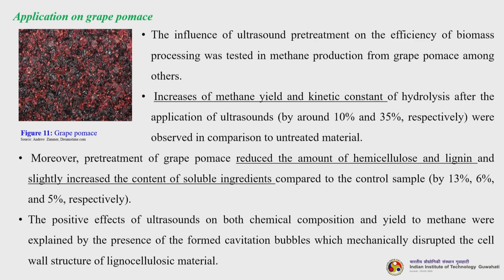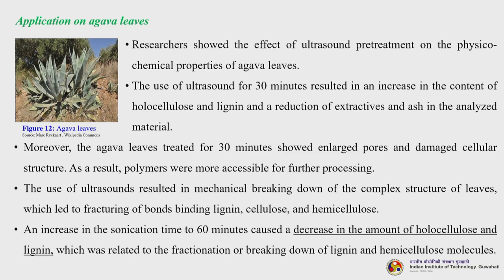Cavitation happens by the formation of bubbles which cause disruption of the cellular structure. For agave leaves, ultrasound pretreatment for 30 minutes resulted in an increase in holocellulose and lignin content and a reduction of extractives and ash. Holocellulose is the amount of water non-soluble carbohydrates. The agave leaves treated for 30 minutes showed enlarged pores and damaged cellular structure, making polymers more accessible for further processing. Ultrasound resulted in mechanical breaking down of the complex structure, leading to fracturing of bonds binding lignin, cellulose and hemicellulose. An increase in sonication time to 60 minutes caused a decrease in the amount of holocellulose and lignin related to fractionation or breaking down of lignin and hemicellulose molecules.